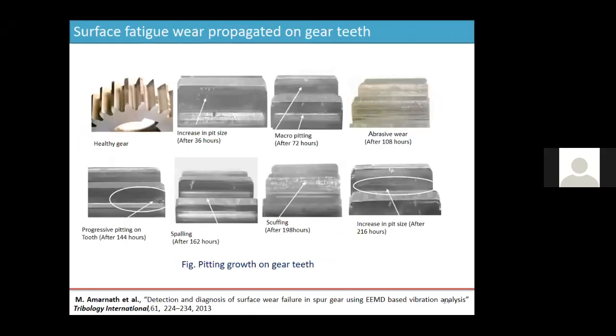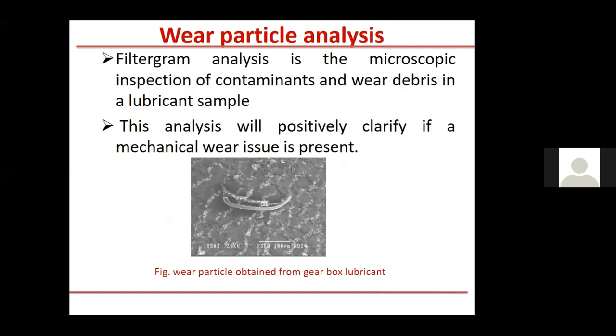In addition to lubrication regime analysis, we have also carried out experiments on wear particle analysis. It is very simple. You take about 5 ml of oil from the gearbox, and you go for wear particle analysis. This is called wear particle morphology. The wear particle morphology will give the details of wear progression in the gearbox. Not only in a gearbox, it can be a bearing, it can be an engine, etc. This is a typical image of wear particles. Based on this morphology, you can get the details of wear propagation in the machine element.